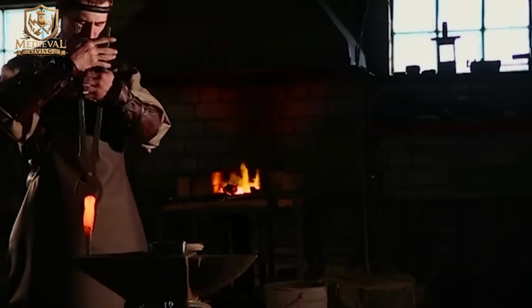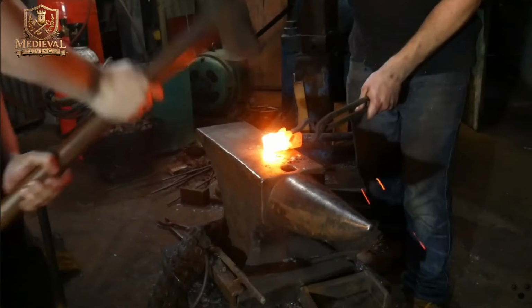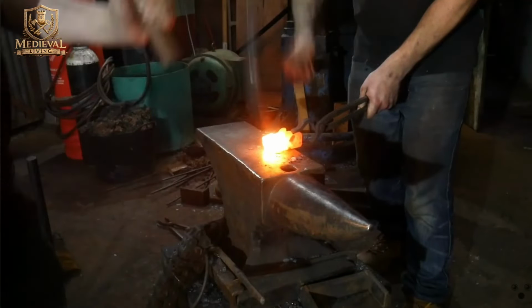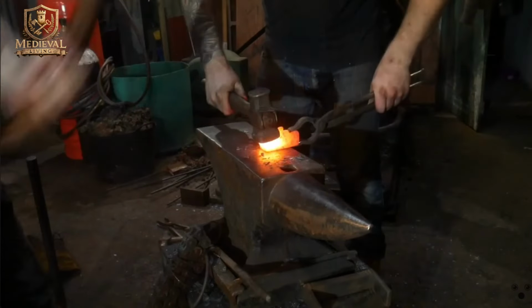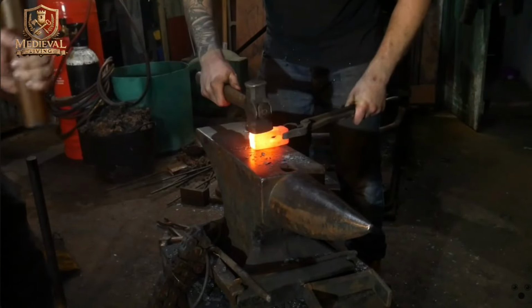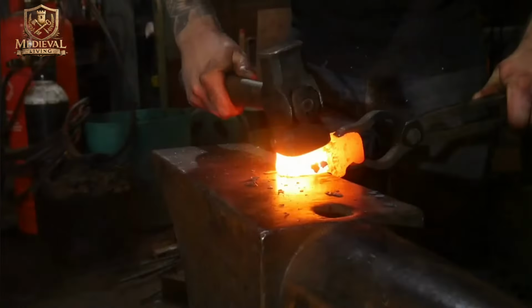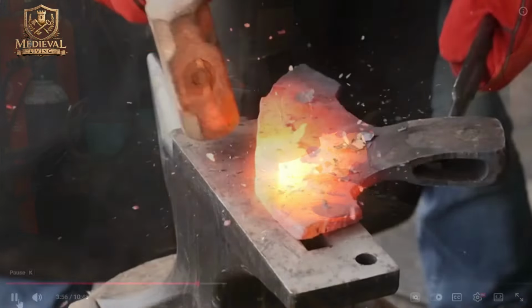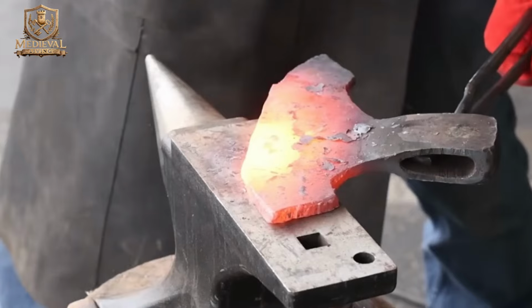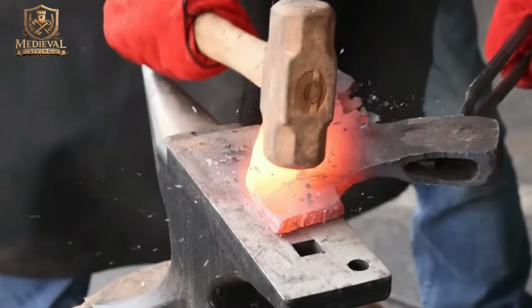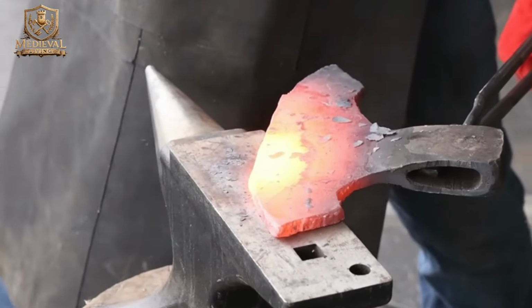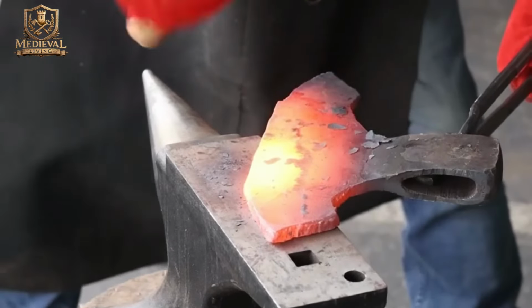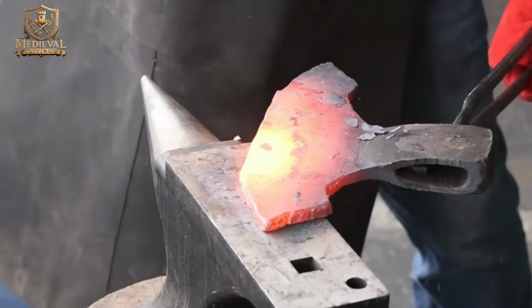When corrosion begins in wrought iron, it encounters these slag stringers. The corrosion path is interrupted. Instead of penetrating deeper, it spreads laterally. Rust flattens rather than drills. The result is a stable surface patina rather than progressive internal decay. The impurities act as internal barriers. This alone would be significant, but medieval iron had an additional, unintentional advantage: phosphorus.